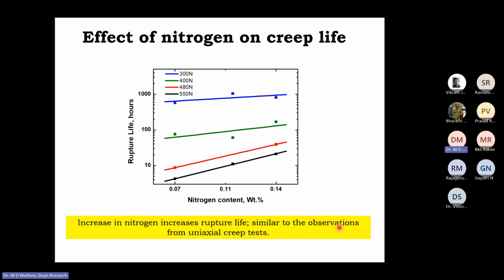So from the SPC creep test, we have determined the rupture life and how it varied with different nitrogen contents. You find that, as expected, as you increase the nitrogen content, rupture life increases, just as the observations obtained from the uniaxial creep test. So we have been able to obtain excellent correlation between the results from these kinds of innovative tests versus the data obtained from conventional tests, but it involves a lot of assumptions as well as empirical relationships.